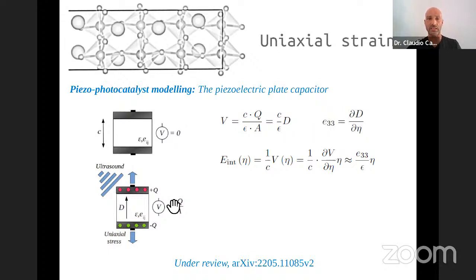So this piezoelectric material, as I said before, is characterized by the electric constant, but also by this piezoelectric coefficient. To make things ultra simple, we are just assuming that this is an isotropic piezoelectric material, so we don't care about any direction other than the one perpendicular to the two plates. In this case, we can easily find an expression for the modulus of the internal electric field. This internal electric field is equal to the potential drop divided by the distance. If we assume a linear approximation for this potential as a function of strain,